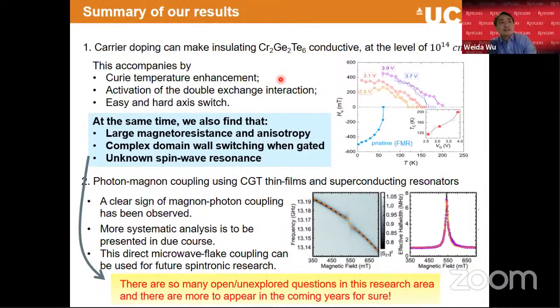Thanks for the nice talk. Sorry, I might have missed it, but for the sodium-doped CGT single crystal, can you just measure magnetization simply to tell whether the TC gets enhanced? I think you use the resonance, FMR, to infer the TC enhancement, which seems to me a much harder experiment.